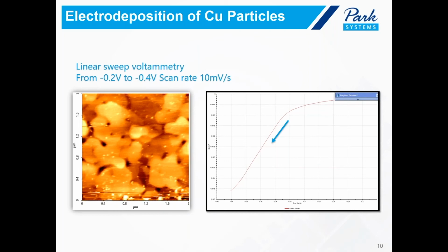Now, after we took that reference image, we started to apply a negative linear sweep voltammetry to the solution. As I mentioned earlier, from negative 0.2 volts to negative 0.4 volts, with a scan rate of about 10 millivolts per second. After we ran the first sweep for about 20 seconds, we took another AFM image of the sample surface, and that is what you can see here on the left.